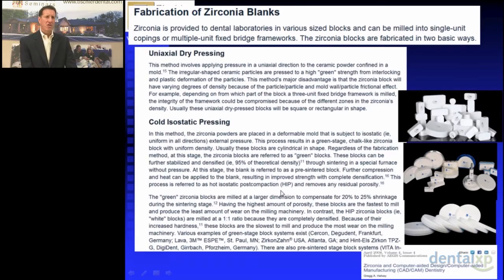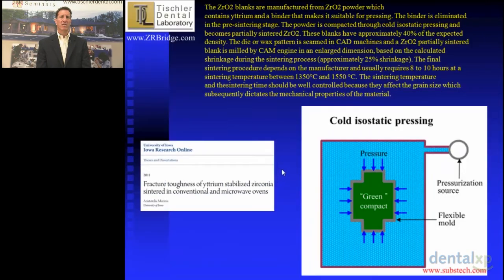The zirconia powder with the yttrium is formed into what's called a green block that's used to mill dental prosthetics. This green block is pre-sintered, and it is actually larger than the final product. So we take this zirconia pre-sintered block, mill a tooth or an abutment out of it, and then it's sintered further, and that final sintered product is quite a bit stronger. The advantage of using these softer green blocks is that they're easier to mill, with less stress on the burrs, and the shrinkage of 20 to 25%, dependent on the company's zirconia, is very accurate. These blocks are made by something called cold isostatic pressing, where the material is evenly pressed into different patterns that the milling machine can then mill into different prosthetics.